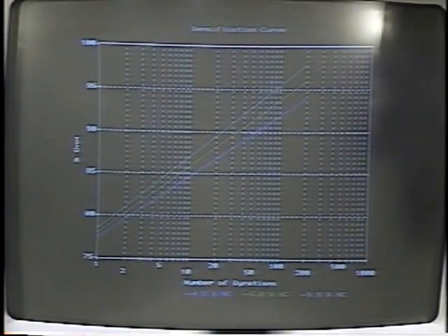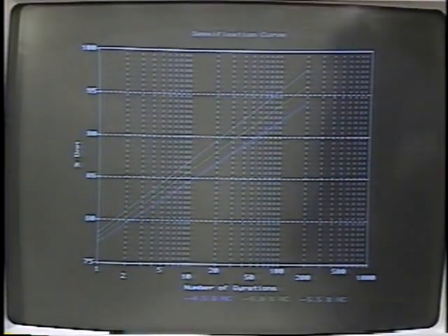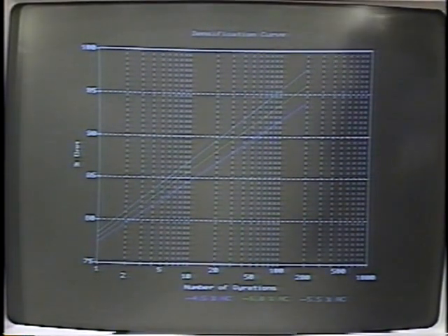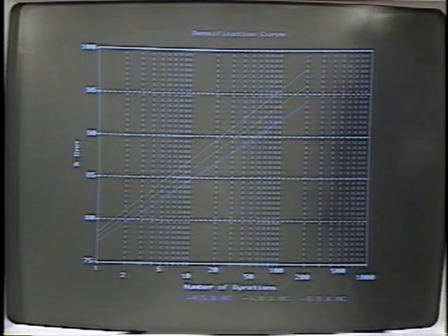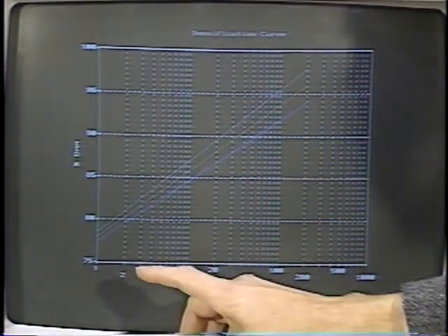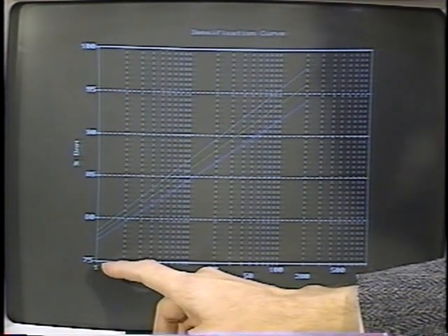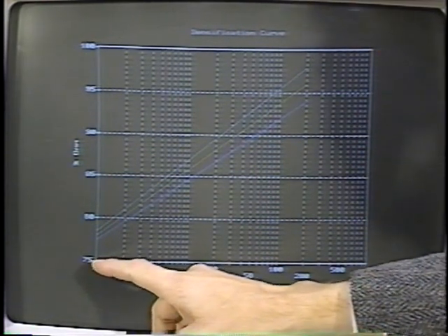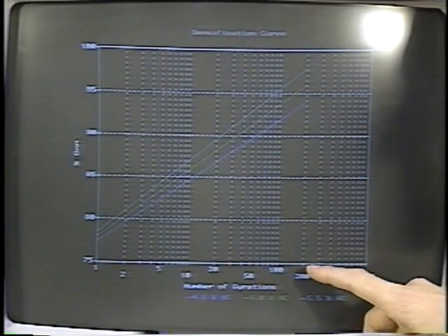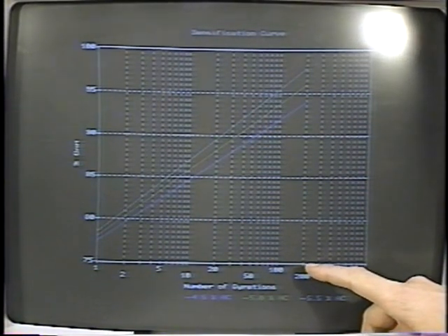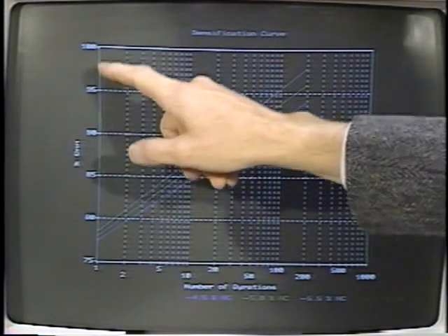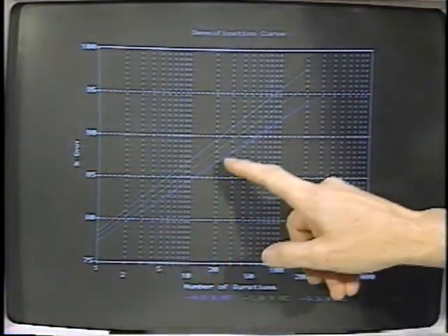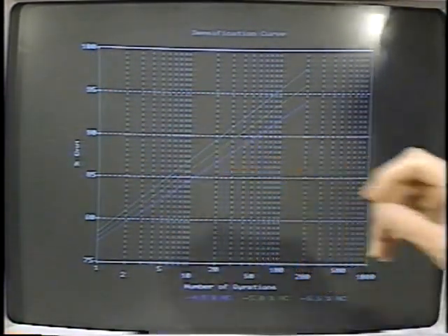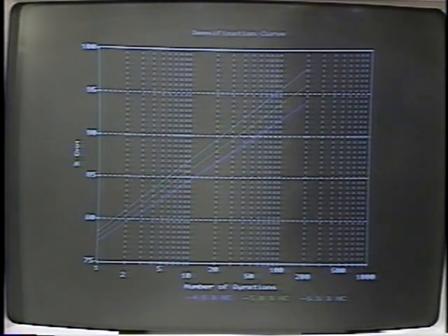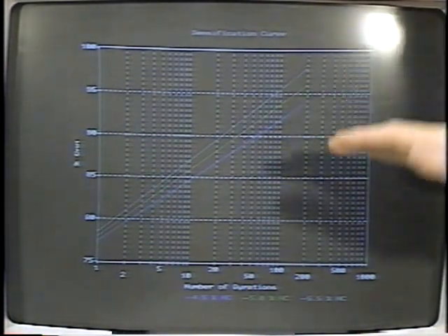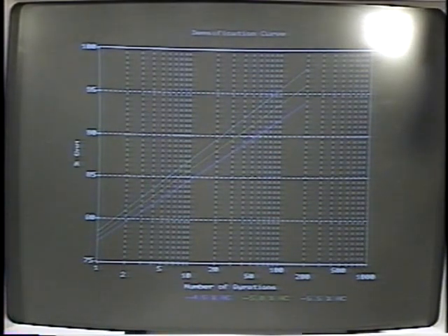As part of the mix design, the user will be looking at the densification of mixes, the compaction of mixtures, and the method by which a mix design will densify. Here we have the number of gyrations in a gyratory compaction machine versus the increase in density. For different asphalt contents, we see that mixtures will densify in different ways, and there will be limits put on and attached to how a mixture densifies.